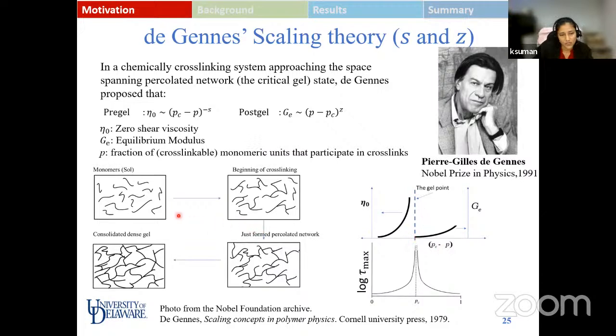So as the system transitions from sol, where the monomers are very nicely dispersed, it begins to cross-link and forms primary cross-links, and with increasing extent of cross-linking, at a certain state it forms the percolated network where all the strands connect to form a space-spanning network. Eventually, after this, as more fractions of cross-linkable monomer units join, it forms a dense consolidated state. The extent of cross-linking is defined in terms of the variable P over here. And he proposed that for a chemically cross-linking reaction, both the values follow a power law.